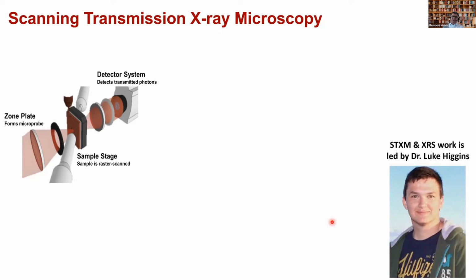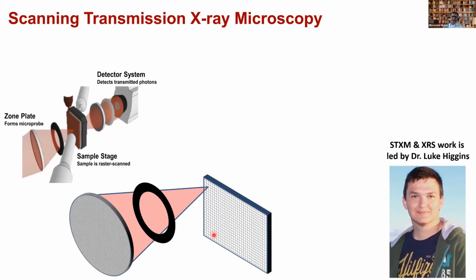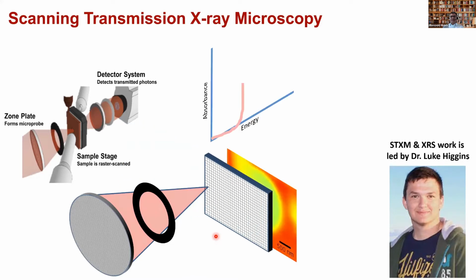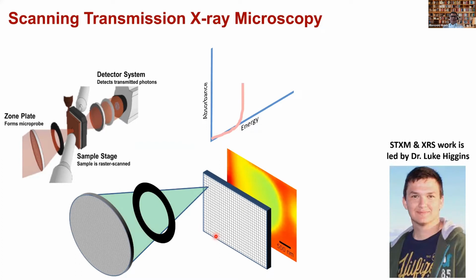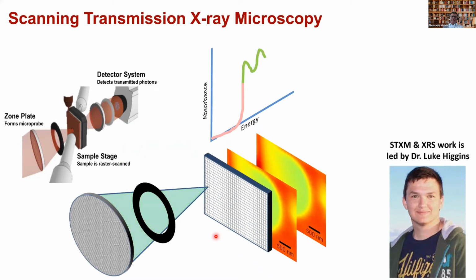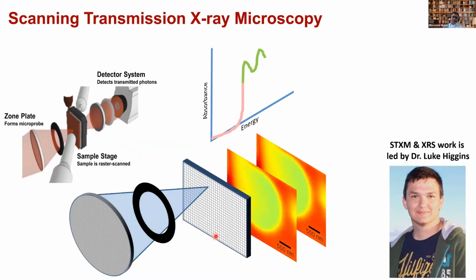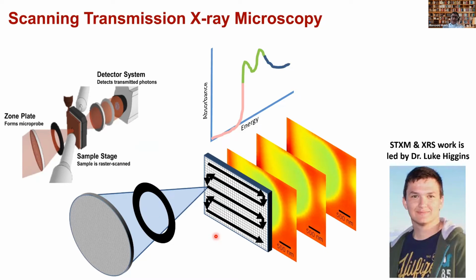So for those who might not know so much about scanning transmission X-ray microscopy, it is a wonderful technique if applied properly, because what it does is raster scanning. But while doing the raster scanning, it also takes a snapshot at every single energy point. So while it's raster scanning in XY, it is also scanning in energy. And so we have energy stack scans, such that we have the full picture of the whole thing with a very high spatial resolution, of the order of 20 nanometers, of the region of interest. So basically, it does not only produce pretty pictures, it also gives full chemical information in addition to very high spatial resolution.